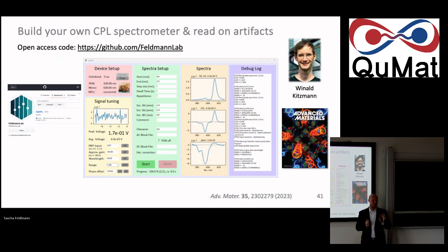So that's one of the predominant artifacts, is linear polarization that looks like circular polarization, because it will still get detected. So we have built a little linear polarization red flag that will show up if your perovskite thin film is actually just a bit strained, and therefore gives you a little bit of linear polarization and you thought it was CPL. And this has now been also implemented by one of the bigger CPL companies. And so they use that as well now as a code. Fortunately, we did not patent this, or we want to be nice, so let's put it this way, so it's for free. The companies now use it, which is a good thing.